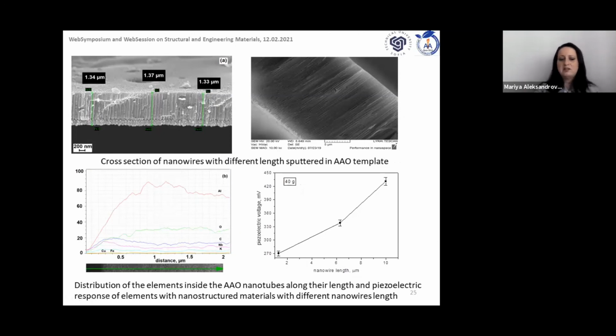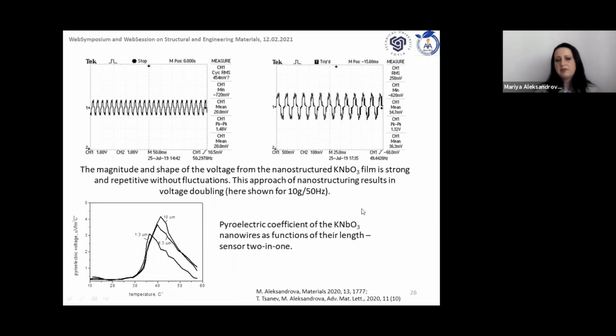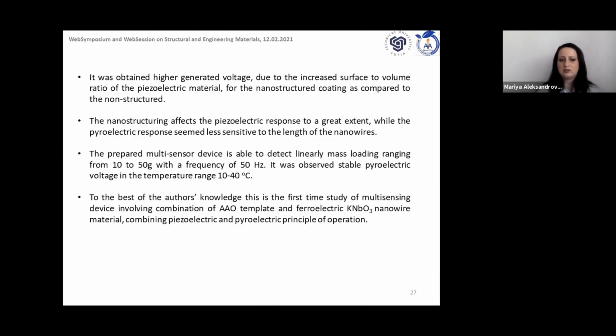So it is demonstrated that there is no disturbed distribution of the components, and a linear dependence on the nanowire length. Again, twice improved piezoelectric voltage, and we also detected some pyroelectric coefficient, which is not so sensitive to the length of the nanowires, but still it allows combining two functionalities in one single device, pyroelectric and piezoelectric.